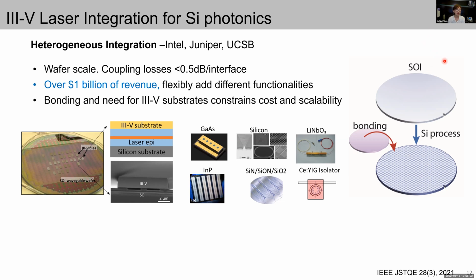And the second part is the thermal budget. Normally the bonding temperature is not a problem. The bonding temperature is only 300 degrees C. So if you pattern the silicon waveguides and put modulators and detectors already on the silicon SOI wafers, then bond and do the post process, the thermal budget should be fine. We are not talking about 500, 600 degree regrowth temperature. We're talking about just 300 degrees C, so it should be fine. I'm not sure if I answered your question.